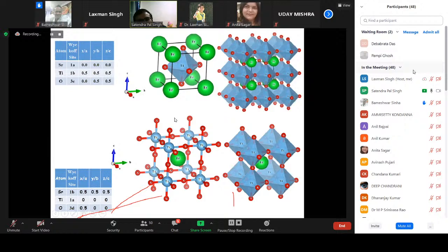So in that manner, if you have a very simple structure, you can determine the position coordinates by knowing only the lattice parameters, the space group, and the density. And you don't need any software to do this kind of study.